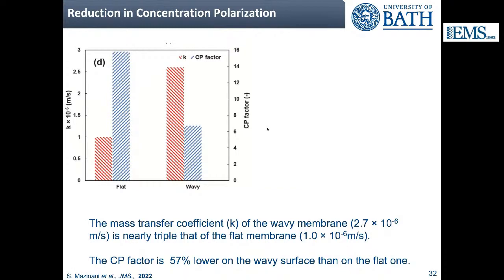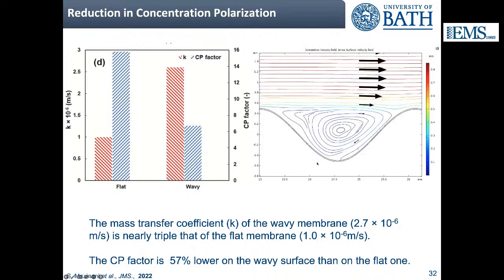To give you some numbers, the mass transfer coefficient is nearly triple that of the flat membrane, and the CP factor is about 57% lower for the wavy surface than the flat one. And the reason is, again, if I go back to those images I showed you initially of the CFD streamline velocity field, because you're generating this turbulence, in this case, in one of the troughs of the wavy membrane, and this recirculation helps lift off any